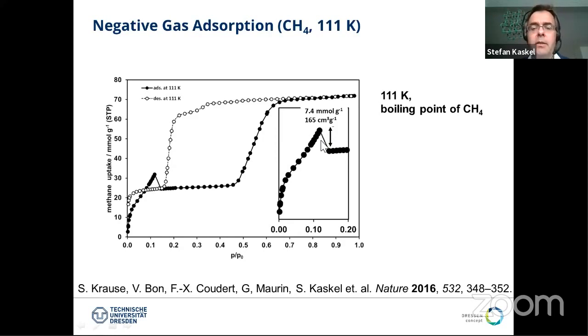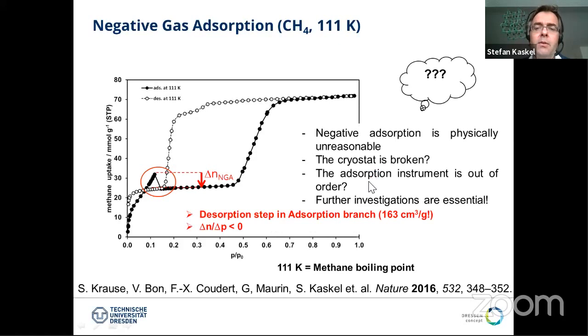And of course, in the beginning I said, okay, this cannot be, negative adsorption is physically unreasonable. Maybe the cryostat had some problems and so on. But in the end, my students measured this over and over and it was fully reproducible. We measured it on a Bell instrument, on a Quantachrome instrument, on a Rubotherm balance, many instruments, and it was always reproducible. So there is a desorption step in the adsorption branch, which is 160 cubic centimeters per gram. This is more than some zeolites can even take up, and it's quite a significant step.